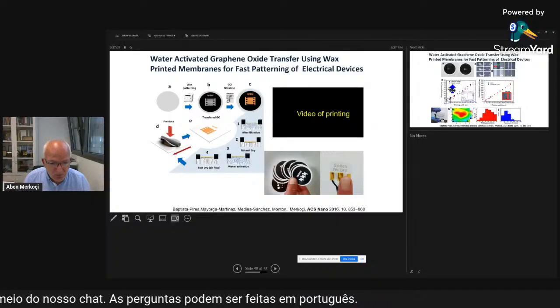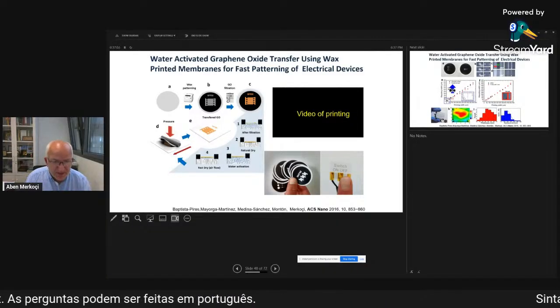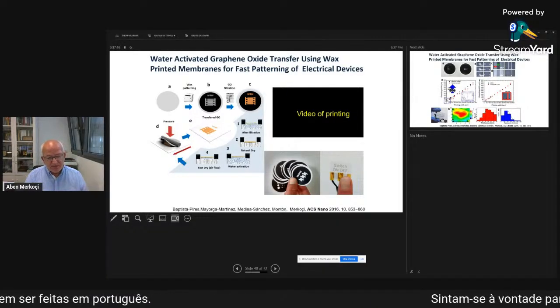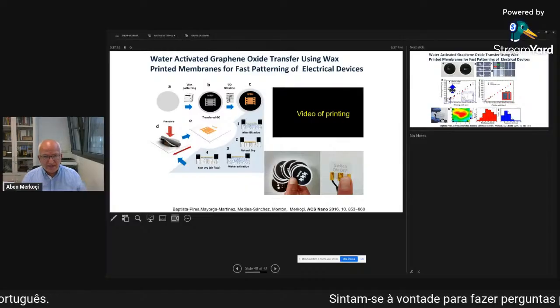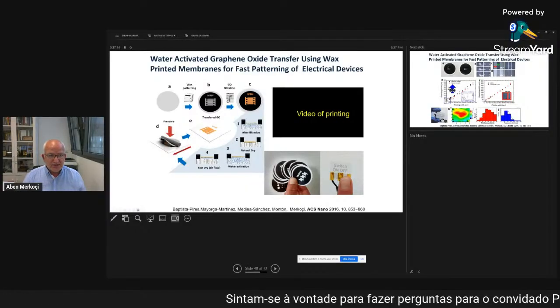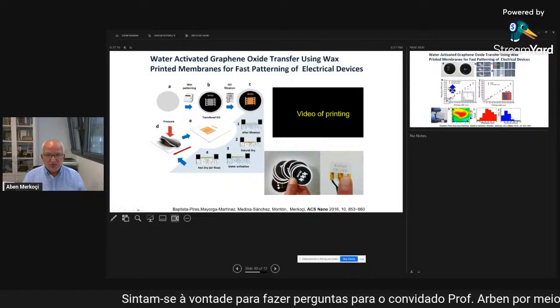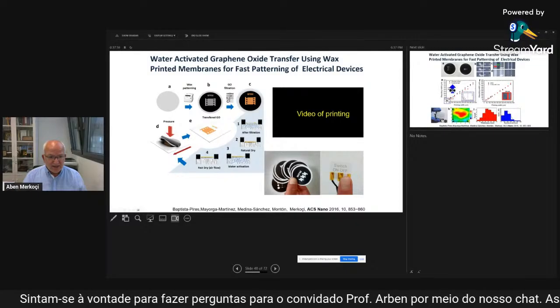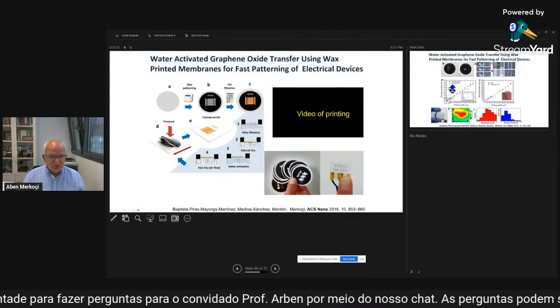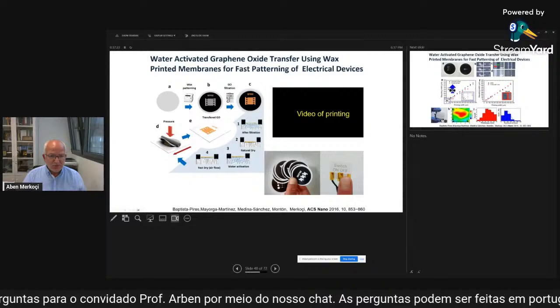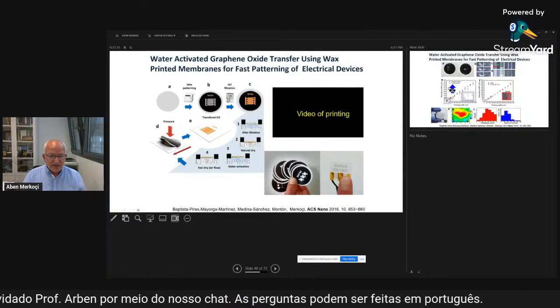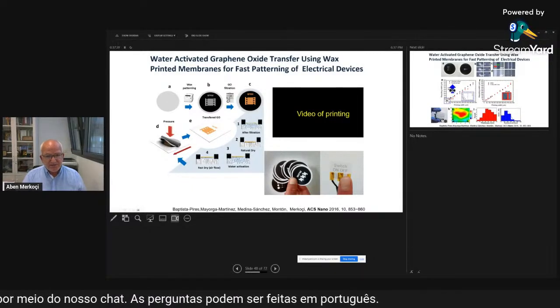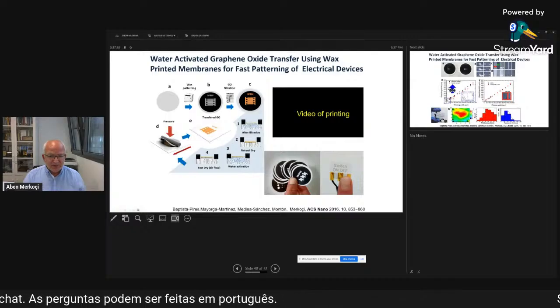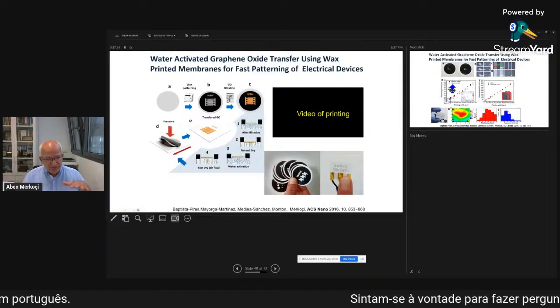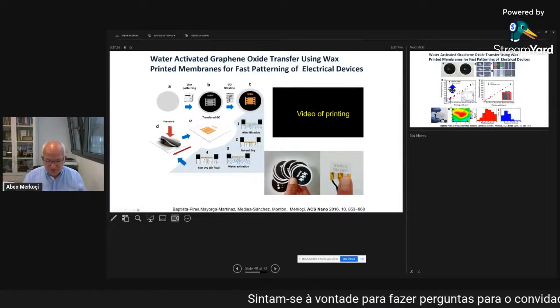So this is how we use, for example, graphene, which is one of the most important materials we are using for our electrical sensors. We have developed the water-activated graphene oxide transfer using wax-printed membranes. This is a patented technology in which we use wax-printed membranes in which we can print any kind of shape, filtering the graphene oxide suspension, and after filtration, drying, water activation, and fast drying using pressure, we can print on any kind of surface.